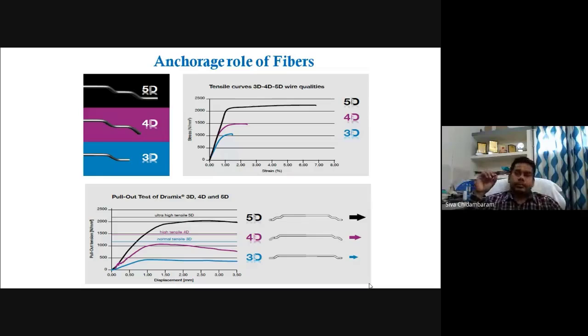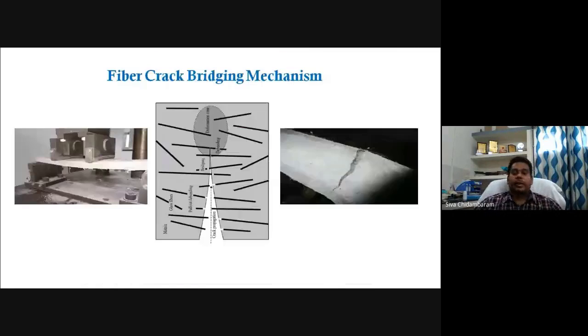Now, if you construct a bridge without abutments, only the portions, it is not a perfect one. It should be anchored with the embankment. Anchoring in fiber is nothing but the end profile or the profile of the fiber. So in hooked-end fiber, the end portion has some deformed shape. With respect to the deformed shape, it will have a wonderful anchorage that will increase the efficiency of your fiber. But in the case of crimped fiber, the shape of the crimped fiber itself will give you wonderful anchorage. This is called the crack bridging effect.